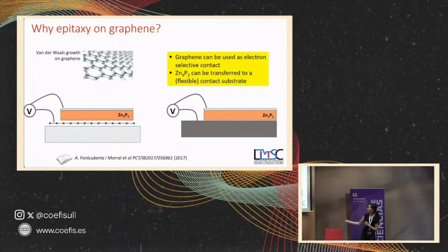The idea here is that you have it directly on an electrode. Graphene is very conductive. You can create another electrode on top and then use the zinc phosphide as an absorber. Or because it's on graphene, it doesn't stick very well, you can just put it somewhere else where it sticks and remove the graphene. This is very easy because of the lack of covalent bonds. And you can put it on a substrate that is maybe a better electrode and create your device. You can do it on plastic. You have many design flexibilities for this.